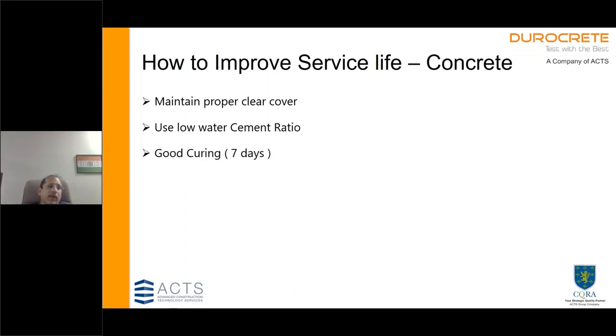So how to improve service life of concrete? One is maintain proper clear cover, use of low water cement ratios, good curing. It has been found that good curing reduces the permeability of concrete. In earlier days they used to give a lot of importance to curing. Today, because of the speed of construction, we cannot give so much time. But 7 days of intense curing is also considered quite good, but it has to be intense and not intermittent curing.